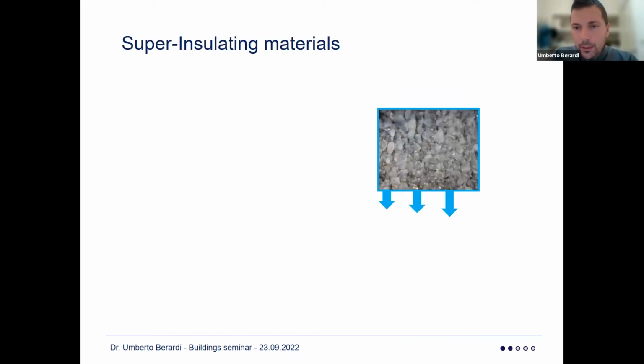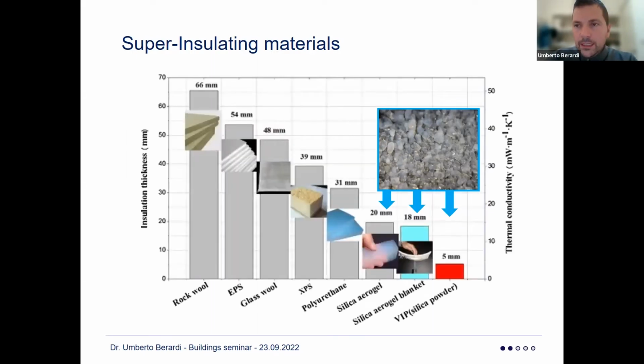Now, let me go to the second and most important topic of today's talk, which is superinsulating materials. When we look at insulating materials, we often tend to present that materials have a thermal conductivity of 0.04 watt per meter Kelvin or in that range, and to insulate buildings more, we basically increase the thickness. However, different strategies, working on materials with a nano approach, have the possibility to reduce the thermal conductivity significantly, from values in the range of 0.04 to values, as you can see on the right of this graph, in the range of 0.01 watt per meter Kelvin.